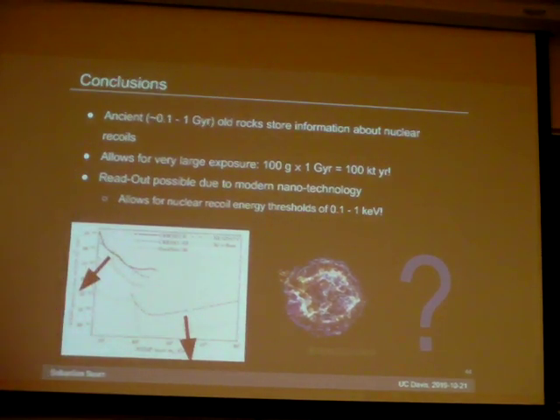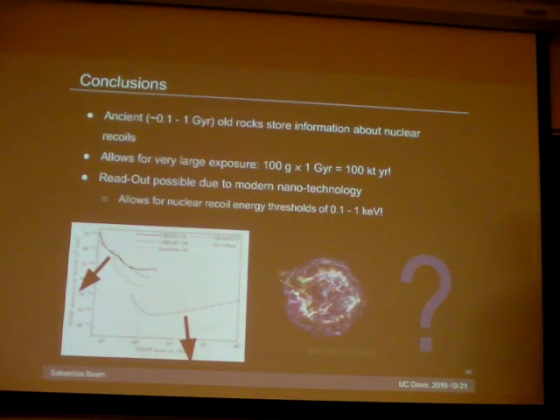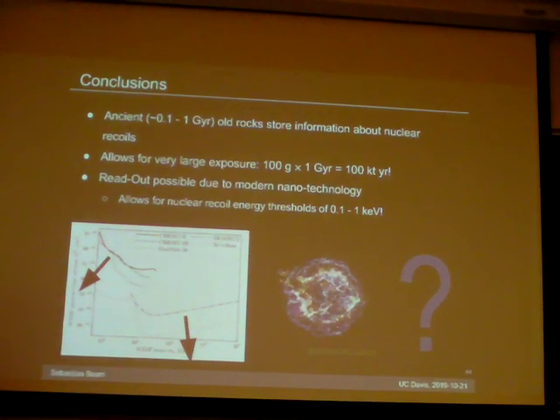Most of the background sources, in particular the radioactive background sources, and what the signal is going to look like, you can go and calibrate in a lab and understand, right? So although there is no first principle description of these tracks, you can do calibrations in the lab. The thing that's hard to do is neutrinos, right? Because it's hard to get a neutrino source with the right spectra and a lot of flux. But again, all they do is cause a coherent elastic recoil. Right. So you just shoot a beam from the outside with that energy. That's right, exactly. You can do the ion calibration. The only thing you can't do is calibrate it by injecting neutrinos and creating your fake signal directly, which would be a little nicer. But yes, as you say, you can do almost what you would ideally want to do. It's hard to get very low energy neutrinos in high quantities. Right.